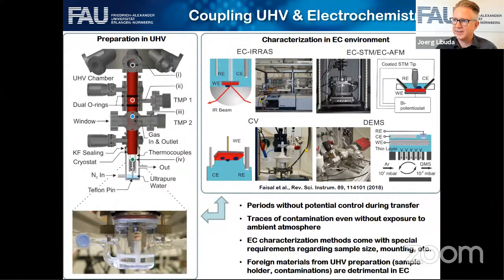And that's the advantage. But of course, there are a few things to keep in mind. It's not that there are no problems. One thing is that during this transfer, there are certain periods without potential control. So you have to think about whether that plays a role or not. Of course, there may be traces of contamination. Even if you don't expose the sample to the ambient, there may be traces of contamination. Maybe this plays a role.